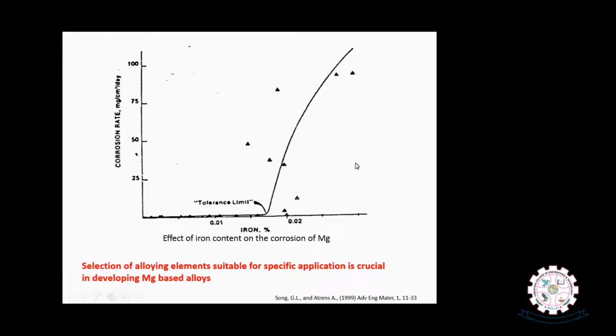Another interesting phenomenon you can observe here is, up to 0.016%, the presence of iron in magnesium has insignificant effect on corrosion property, whereas when the percentage of iron is increased beyond 0.016%, then you can see the corrosion rate is gradually increasing. In fact, it is shooting up like anything. You can see up to 0.02, the corrosion rate is higher compared with the 0.01.